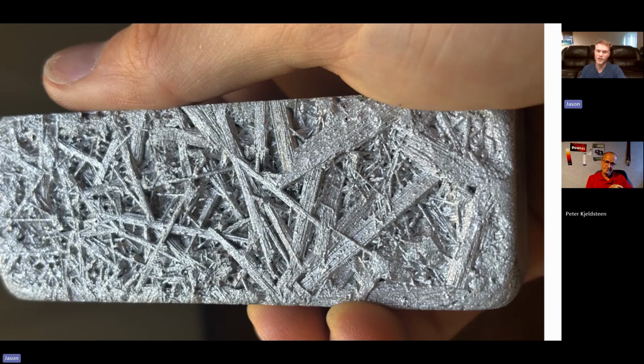And so these are all aluminum copper intermetallic rods. The level of the liquid was all the way at the surface of these rods, but as it cooled, the liquid receded as it densified, and the rods remained as they had already solidified. And so that's really cool, I think. I mean, when I first saw this, I was like, oh my gosh, this is so cool. I mean, to see these huge metal crystals actually crystalline rather than on a polished surface is